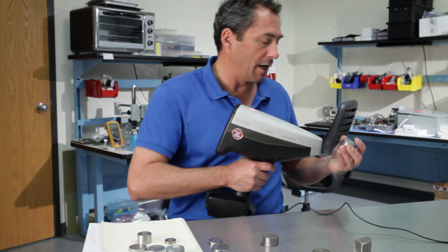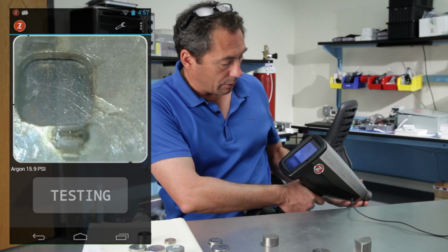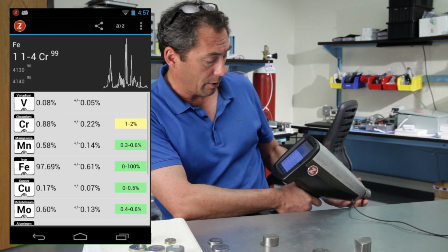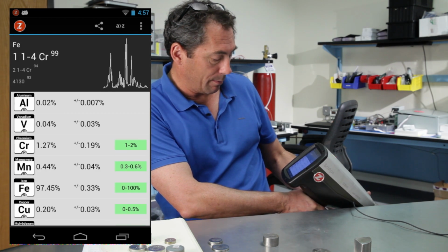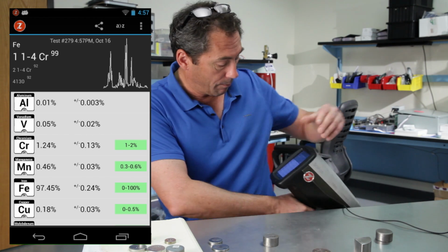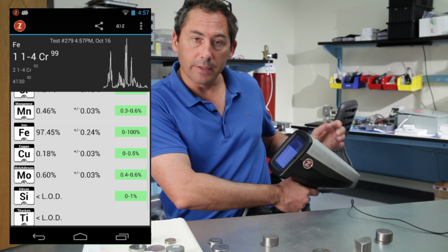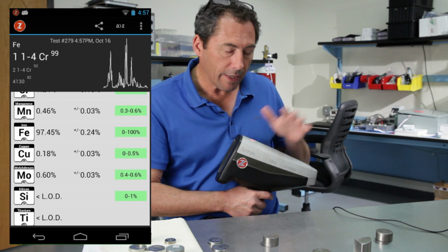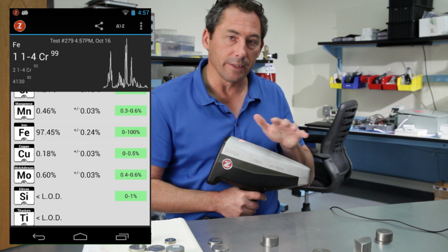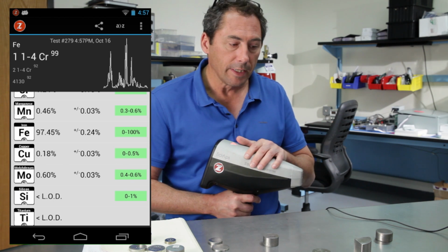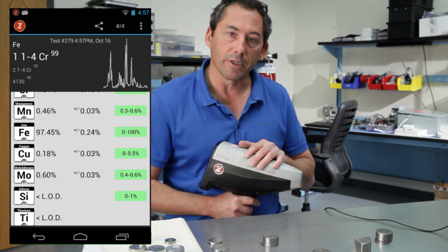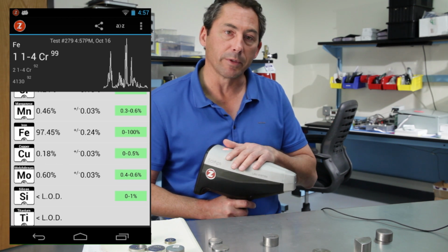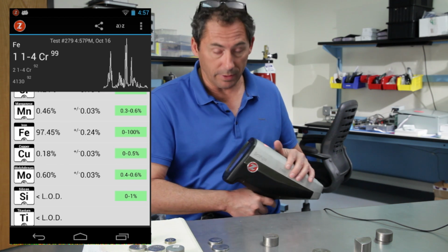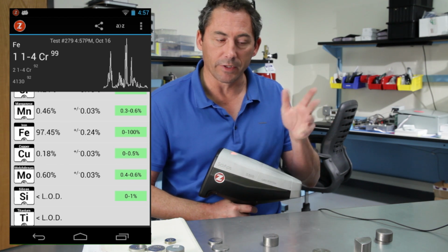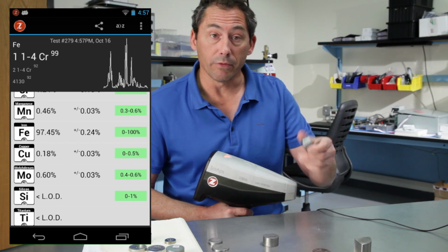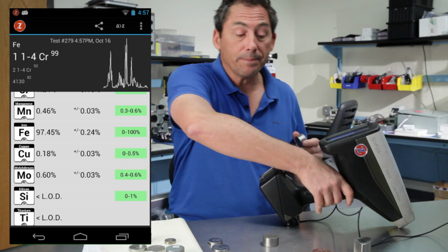Let's start out with a very common refinery alloy. Here's 1 1/4 chrome. Pull the trigger a couple of seconds, you get your 1 1/4 chrome. And you see it's a nice chrome result, about 1.2%, which is typical. Something worth pointing out is the moly as well, down around 0.5%. For a lot of LIBS units, measuring low concentrations of moly is very difficult. Moly is a very refractory element, and exciting it into the plasma is hard. That's where the powerful laser, the good spectrometer, and the argon all help. So as you can see from that, we can very quickly measure that 0.5% or so moly. That's critical to measure in this refinery alloy, this 1 1/4 chrome.